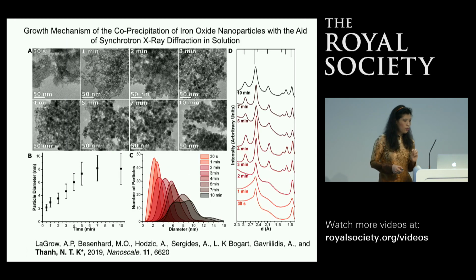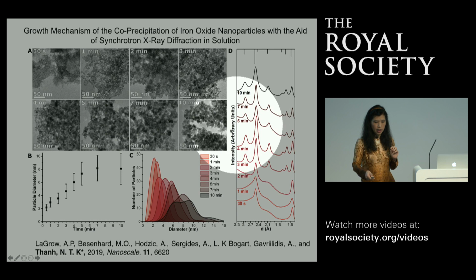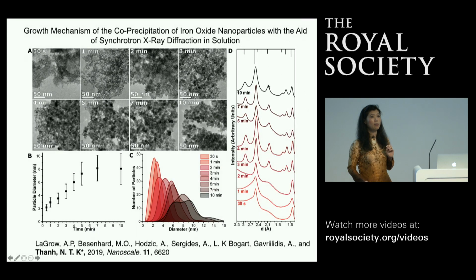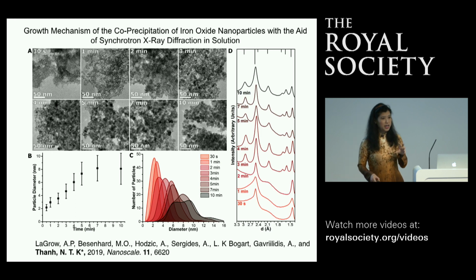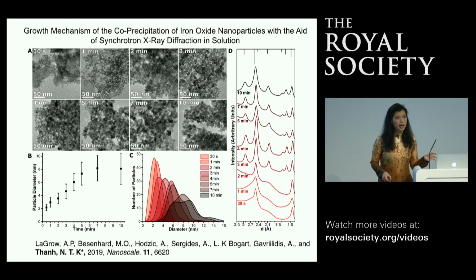So with this work, we look through the TEM at different times and see the evolution from 0 to 10 minutes, and we can see that in a couple of minutes we could form the different phase, so we can monitor the reaction.